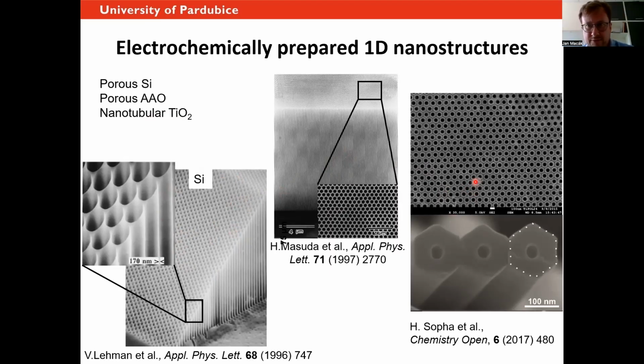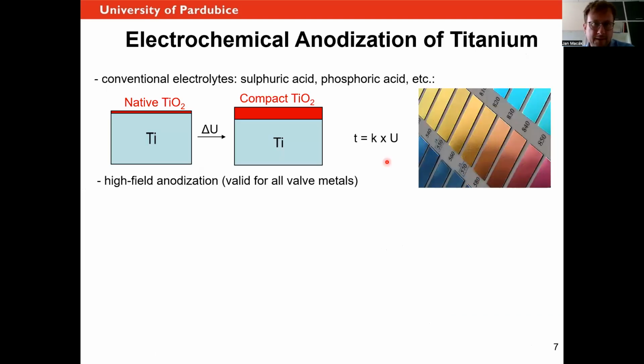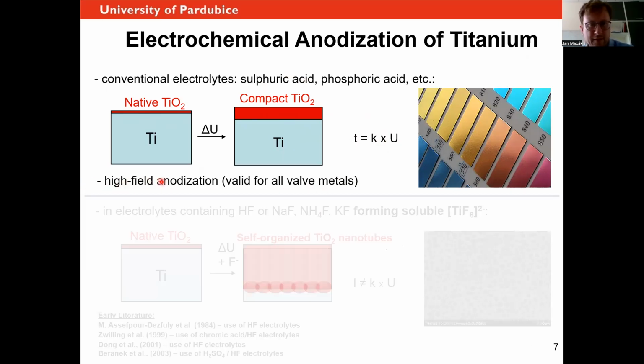We grow them by anodization of titanium, as I said. And in the next few slides, I just want to be a little bit more detailed about how it works. So when you do it the way I just showed in the beaker, and you apply some 10, 20, 30 volts in conventional electrolytes like sulfuric acid, for instance, you will do nothing else than just thicken the oxide, because there is always native oxide, which you will just grow thicker. And the thickness of this oxide will be proportional to the applied voltage. This is a very well-known mechanism of oxidation, which follows so-called high-field anodization.